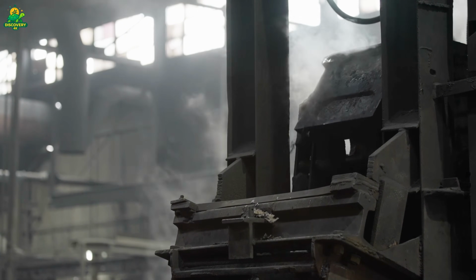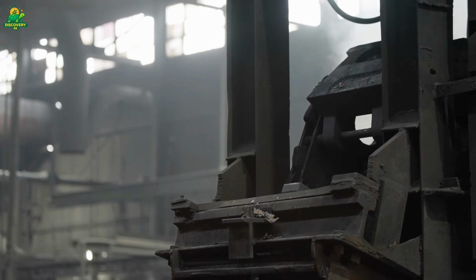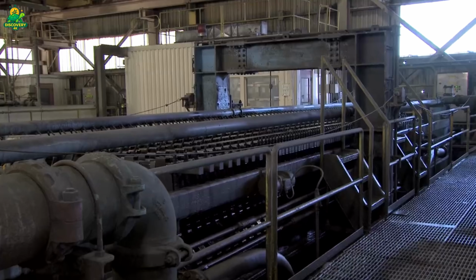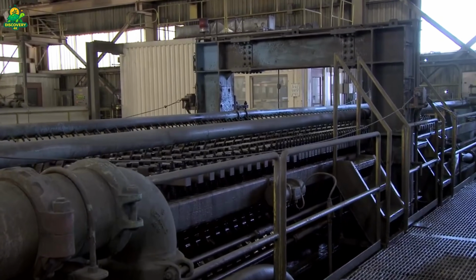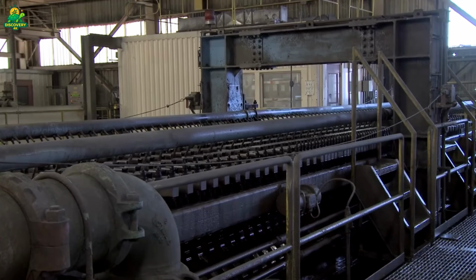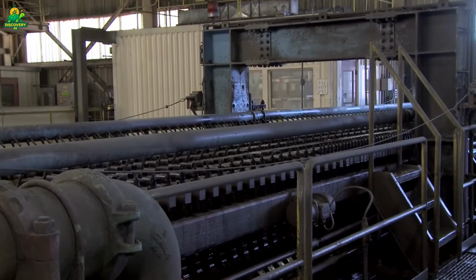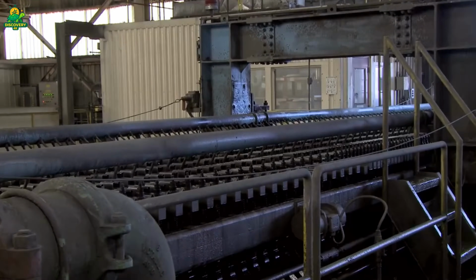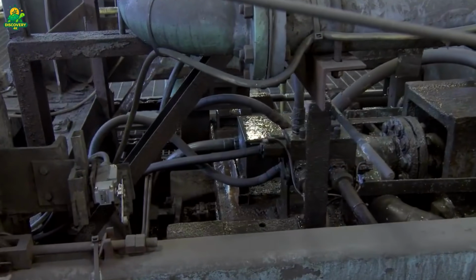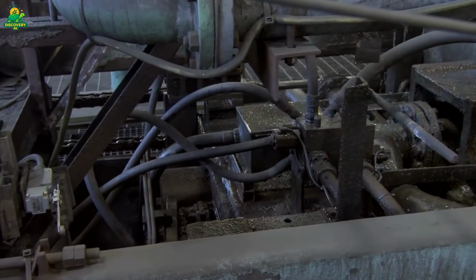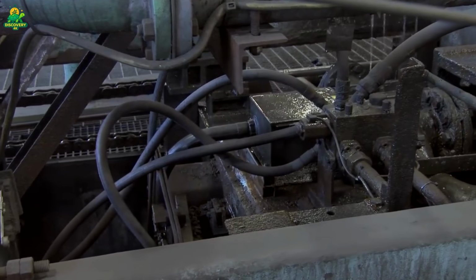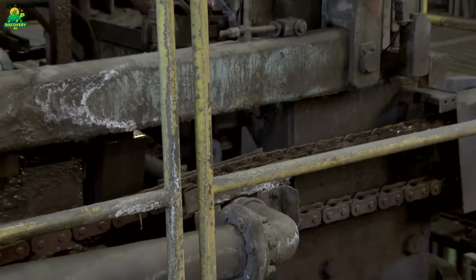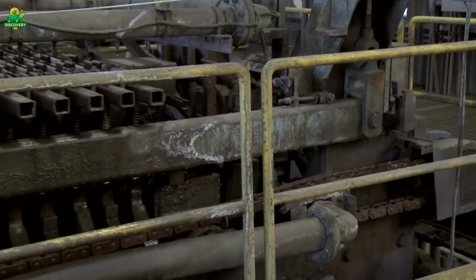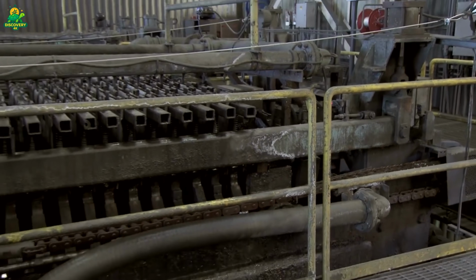Copper extraction relies on a process called froth flotation. Air bubbles are pumped through the slurry, and chemicals are added to make copper particles attach to the bubbles. As the bubbles rise to the surface, they carry the copper with them, forming a concentrated foam. This foam is collected and processed further, increasing the copper concentration from less than 1% to around 25 to 30%.